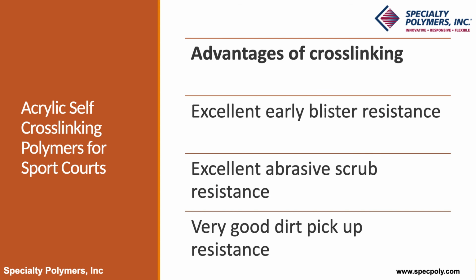So you can see that if you compare performance with and without crosslinking using the same acrylic backbone and surfactant package, you get better early blister resistance with the crosslinking. This gives the paint maker some insurance against failures due to sudden rainstorms. The paint with the crosslinking also has much higher scrub resistance, which could indicate better abrasion resistance, and it has better dirt pickup resistance.